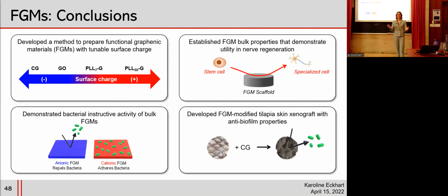So, conclusions with this FGM work. We developed a class of functional graphenic materials where we could tune the surface charge of the material by adding on different chemical functional groups on the surface. And we established the bulk properties of these FGMs, which demonstrate utility in an electrotherapy treatment for nerve regeneration. We next demonstrated the bacterioinstructive activity of the bulk FGMs and applied the FGMs in a xenograft model where carboxylated graphene, the most negative, was found to inhibit biofilm formation the best.